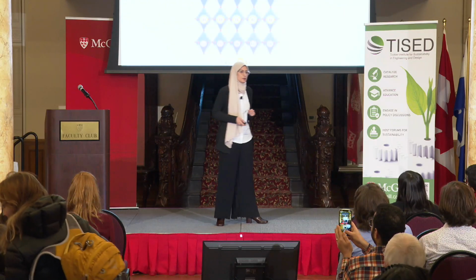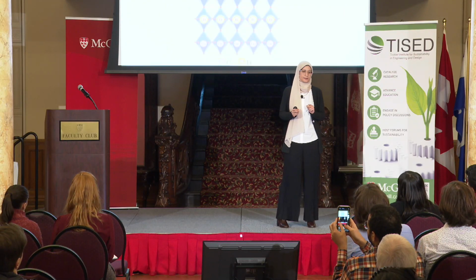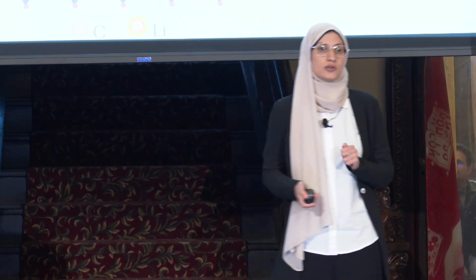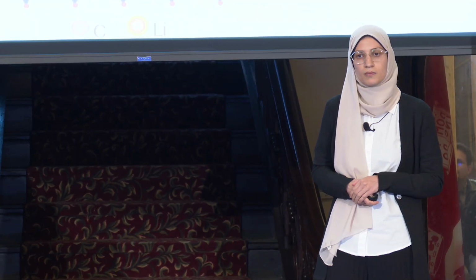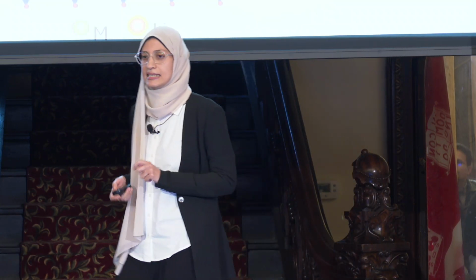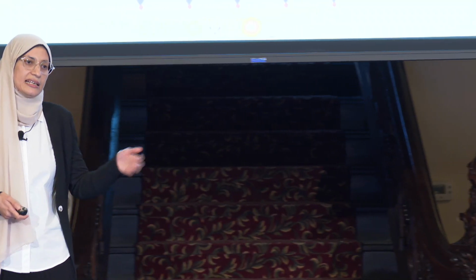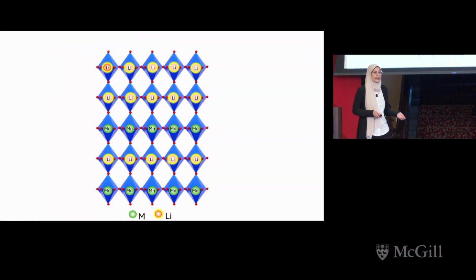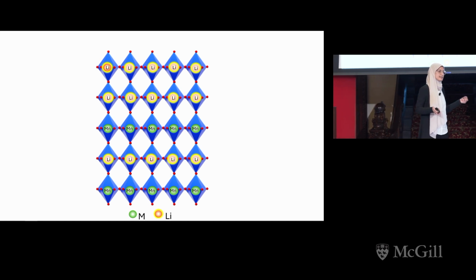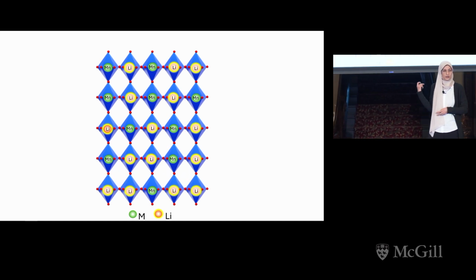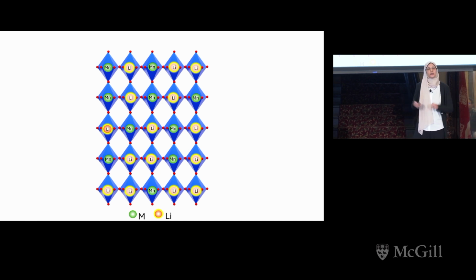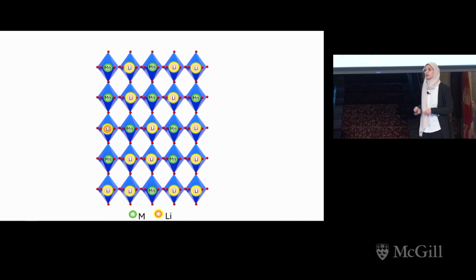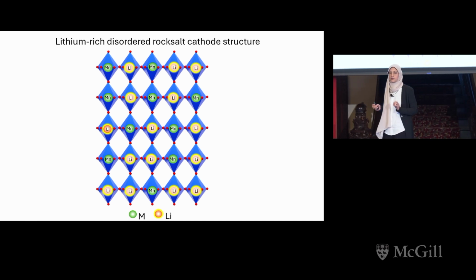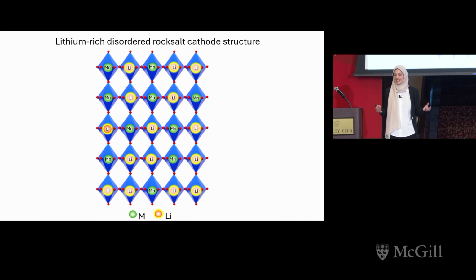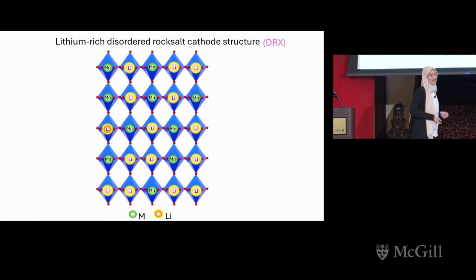So now let me introduce the material that I chose to work with. This material has more lithium in the structure. Also, it can be made of manganese instead of cobalt. And unlike the layered material, the lithium ions and manganese in this material are randomly distributed in the structure, as you can see in this image. So let me tell you the name of this material. This material is called lithium-rich disordered rock salt cathode material. I know the name is too long, but the good news is you can just call it DRX.